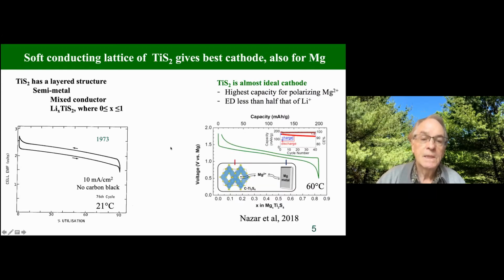So I said TiS2 was good for lithium. Linda Nazar, who's speaking a little later, showed that TiS2 is also very good for magnesium. And the plot I show of hers here is for the spinel phase. So TiS2 exists in 2 different phases. And you can see very little polarization, very good cycling retention. But this is at 60 degrees centigrade and the lithium is at 21.